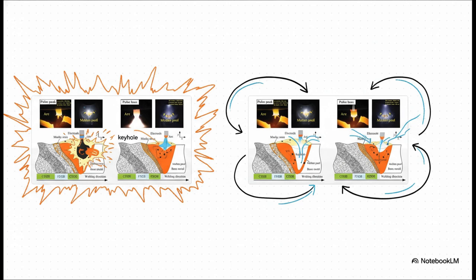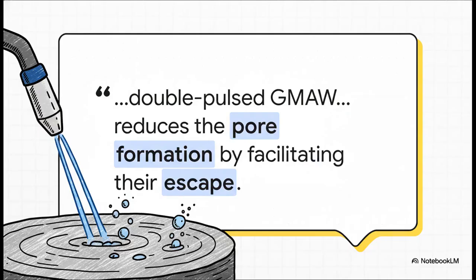Then, during that low current base phase, the pressure lets up and the molten metal flows right back in to fill the hole. This active management of the molten pool creates a weld that is so much stronger and more consistent. And this gets us right back to that pesky porosity problem.